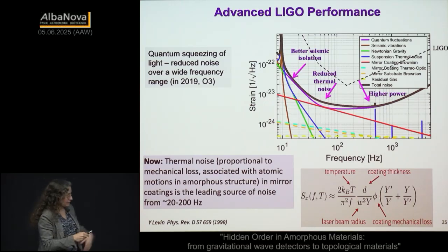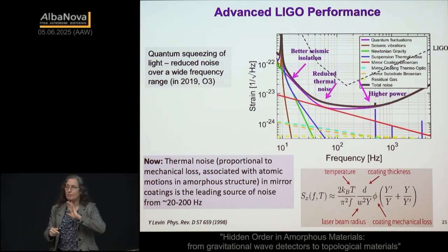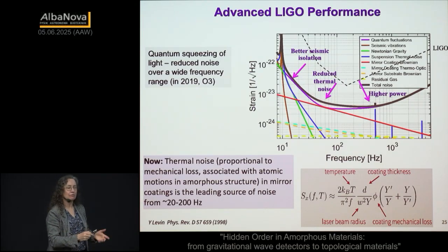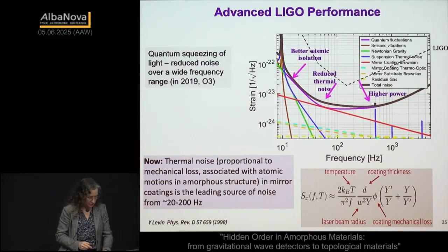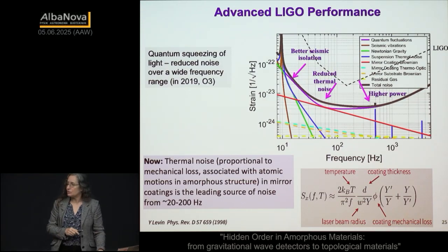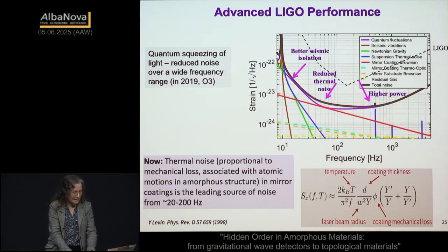In the coatings. And it turns out silica has, the amazing power of silicon and silica, both separately. So silica at room temperature has this enormous dip. It is an amazing material at room temperature and only at room temperature. And so that is the leading source of noise right now. And it's limited right now by the high index layer, which is the titania-doped tantala.